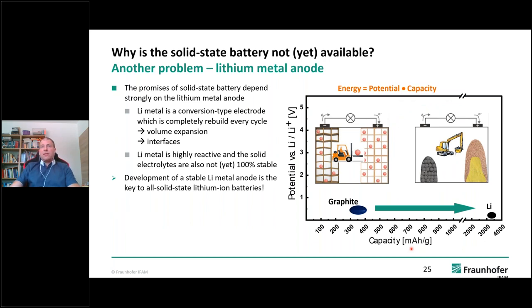And another problem is the lithium metal anode. I told you that the lithium metal anode is very good and has a 10 times higher energy density capacity than graphite, but unfortunately it has some more problems. When we compare graphite with lithium, graphite is a so-called intercalation anode, which means you can imagine it as a cupboard where the lithium ions are just put inside and taken out as much as we need. So the cupboard stays the same and we can just put lithium in and pull it out.